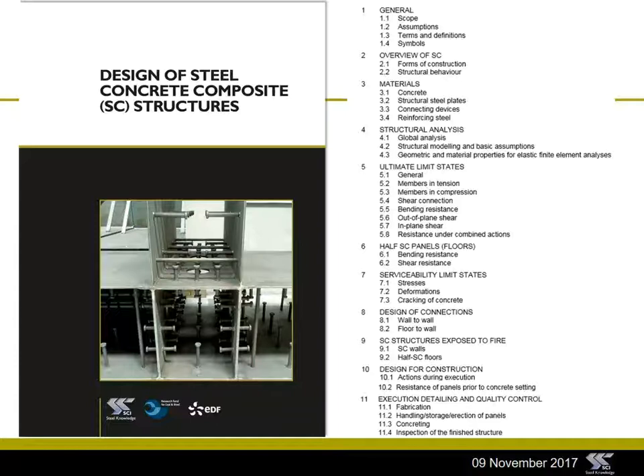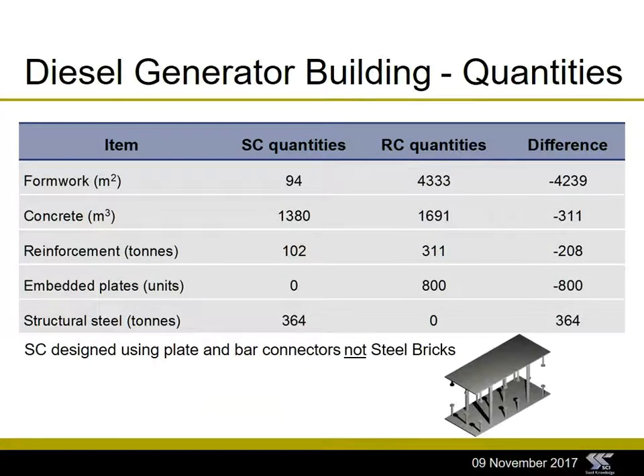And one thing we did in that project was we took the same building that we looked at in this project, and we designed it using a generic form of SC construction. So it's two plates connected by bars. And this shows you a comparison of quantities between the reinforced concrete designs, of which there are many, and the SC construction. And so the obvious ones, you see a huge reduction in formwork. The formwork in the SC case is just for the foundations. There's a reduction in quantity of concrete because we were able to make the walls thinner. A big reduction in reinforcement. Embedded plates are completely eliminated. But of course, now you've got structural steel plates, which you don't have in the concrete version of the building.